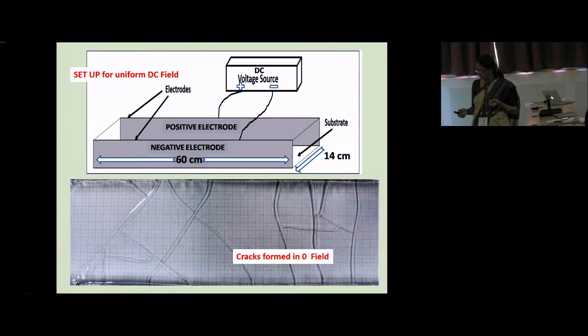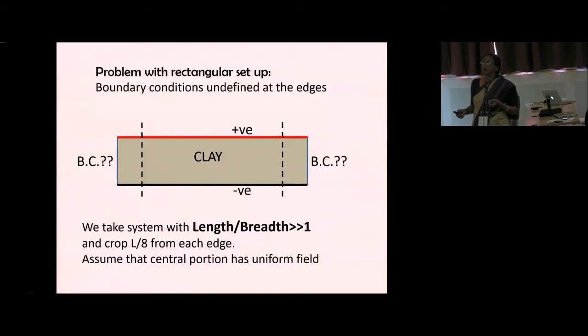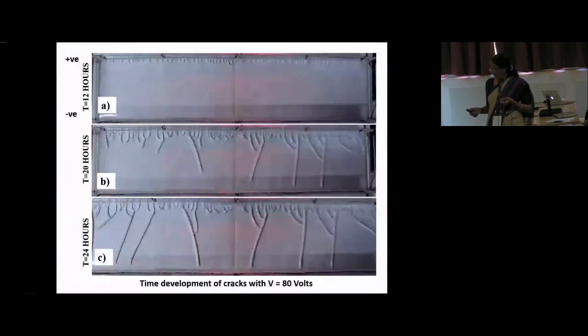And what happens if, now the problem that I spoke of is that at these two boundaries, the boundary conditions are not well defined. So we have chosen a large aspect ratio. The length is much larger than the width of this box. And we ignore the two edges. When we analyze the pattern, we cut off the two edges and look only at the central portion. And in the central portion, we can assume that the equipotentials are parallel lines, uniformly spaced. And this is what we see.